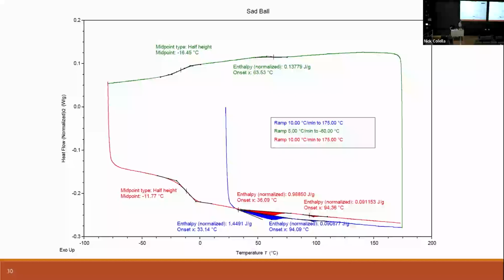So one thing we want to be careful of when doing DSC is we don't want to degrade your polymer so much that it's going to turn into a gas inside the DSC, because then it's going to coat the DSC cell and contaminate it, and it's a pain to clean. So we typically heat up for organic materials to about 220. That is usually a pretty safe temperature for most hydrocarbon type materials.